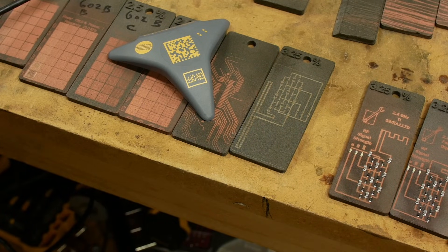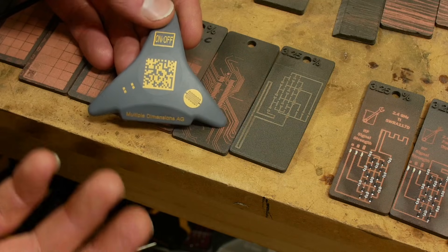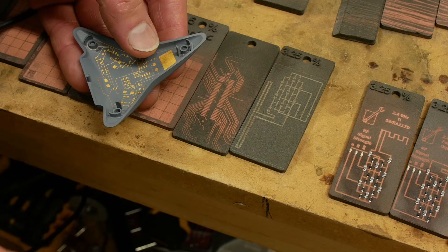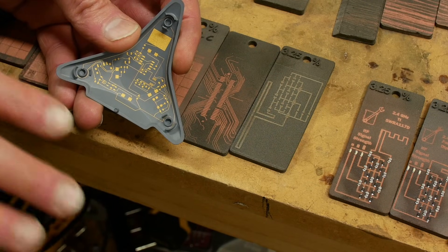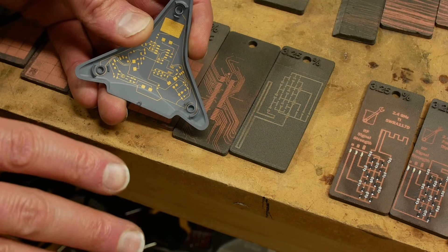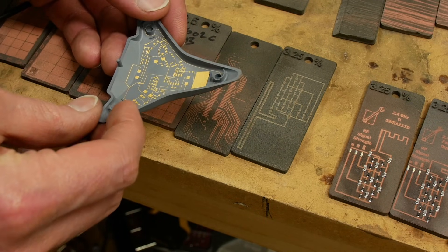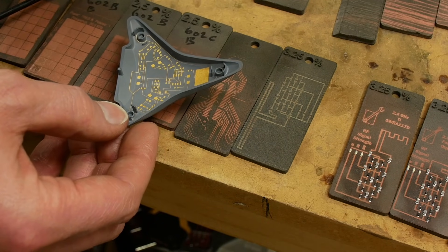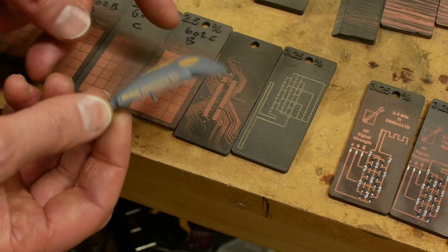Let's talk about putting traces on three-dimensional parts now. By the way, I should have mentioned that this whole process is actually a commercial thing called molded interconnect devices. And these are commercially used to do things like three-dimensional antennas in cell phones and really mechanically constrained places. Also, again, like cell phones, where you need to have wiring and mechanical support all jammed together in a super tight space. And you just can't afford to have like a circuit board in addition to like a plastic standoff. And so how do these guys do it? I just said the focal plane is really narrow. So you actually have to have dynamic focus if you want to make a part like this, where either there's a moving optic or a moving support structure to get the focal plane at the right place if you have a curved surface like this.